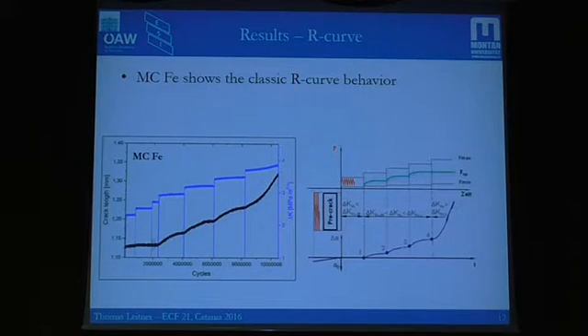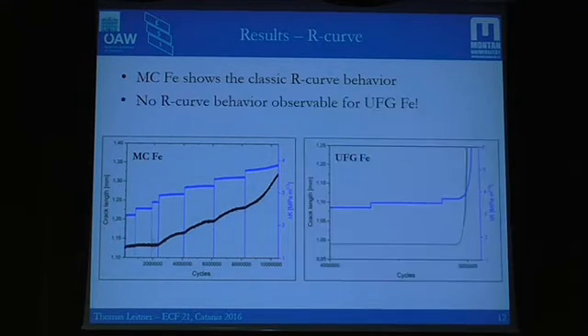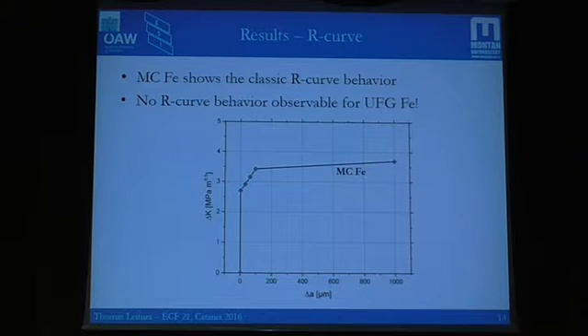So let's come to some results of my studies. What I find for microcrystalline iron is that it shows the classic R curve behavior quite well, very comparable to our schematic here. But when we look at the ultrafine-grained iron, we don't see this R curve behavior; instead we get no observable crack extension until we reach the long crack threshold, where the crack starts to grow until failure. Shown in the form of the cyclic R curve, this is an example for the microcrystalline iron, a classical cyclic R curve. However, for the ultrafine-grained iron, this changes and it seems to get much steeper than for the microcrystalline microstructure. So how can this be explained?